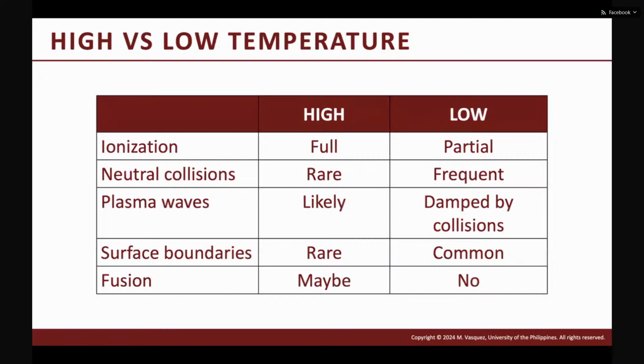So comparing now high and low temperature plasmas, at high temperature you achieve close to full ionization. That means all of your gas particles are ionized, while in the low temperature or cold plasma, you have partial ionization. And usually this ionization is really low, especially at low pressure or vacuum. In terms of neutral collisions, it's rare for high temperature because most of them are now ionized, as compared to low temperature plasmas. And plasma waves are not observed in low temperature plasmas because they are damped by